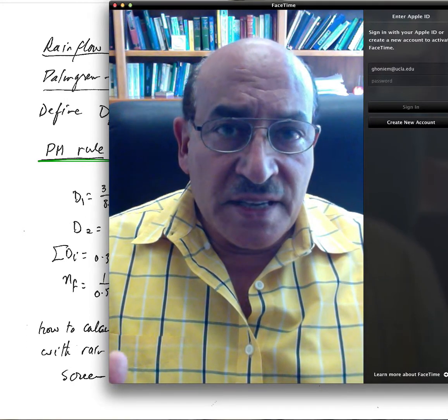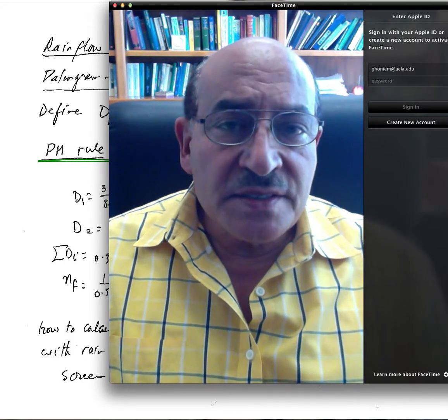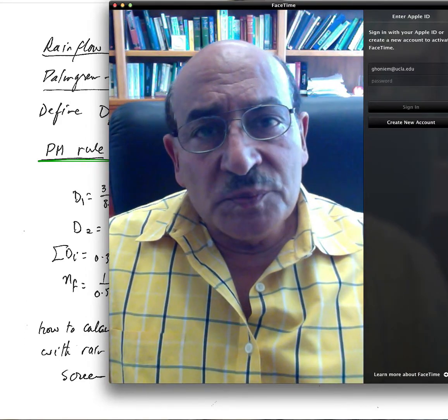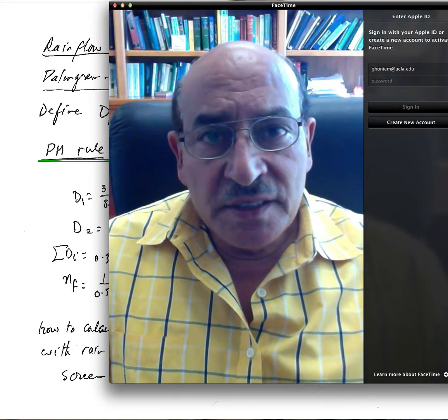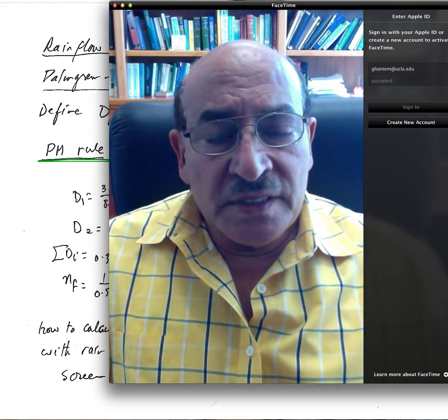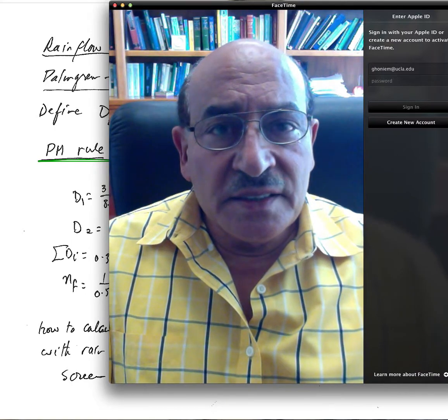Well, in this case, we have to go through a step, and this step would be to summarize all of the stress components into an equivalent von Mises single value, and this single value will be for the alternating part, another single value for the mean part, and then we make a correction for the effect of the mean using one of the fatigue relationships that we've learned before. And once we do that, then we can use the SN curve and successively add the damage.